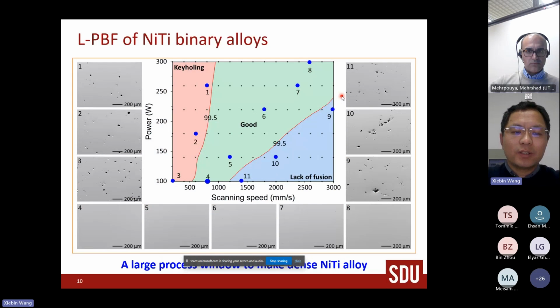And then we printed these samples and did a process optimization. And it's very similar with other alloys. For example, with a high energy input, you get a lot of keyhole pores, and with low energy input, you get a lot of lack-of-fusion defects. But there's a large process window to get dense and almost defect-free samples.